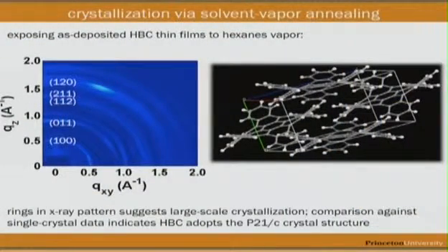What we can also do is we can take a single crystal of this material, and we can figure out the single crystal structure. We can then compare this X-ray diffraction pattern against that from single crystal, and we confirm that this HBC, when it's crystalline, adopts this P21/c crystal structure. So what that basically tells us is how these molecules are organized relative to each other. Okay? From this X-ray diffraction pattern, you'll also notice that the intensity along these arcs is not uniform. You see, for example, in the 100 reflection, that it's slightly more intense in the equator, and in the 120 reflection, that it's more intense here.